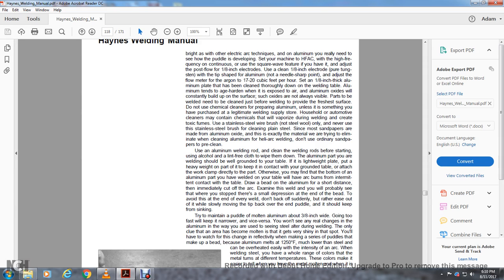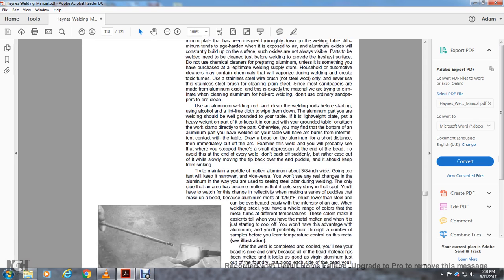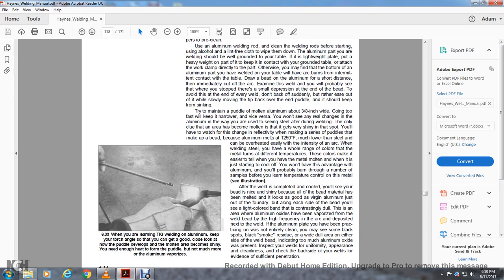Draw the bead with aluminum from a short distance and immediately cut off the arc. Examine the weld, and you will probably see that you stopped with a small depression at the end of the bead. To avoid this at the end of the weld, do not back off suddenly, but rather ease out of the weld while slowly moving the tip back over the end of the puddle, to keep it from sinking. Try to maintain a molten puddle about 3/8 of an inch wide.